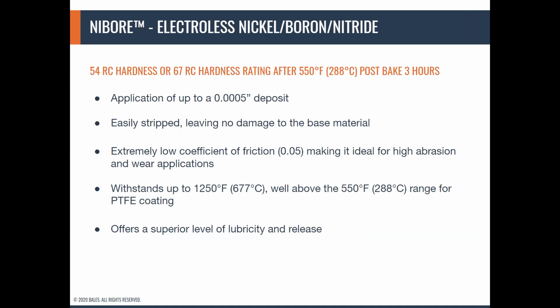Electroless Nickel Boron Nitride, our NIBORE. What's nice about this is now we can add a post-bake option to it. NIBORE, as applied, sits around a 54 Rockwell, which isn't too bad. It's typical of most heat-treated steels. Also, if you post-bake it at 550 for 3 hours, now you've achieved a 67 Rockwell. As you saw in the earlier slide, the hard chrome is a 72 Rockwell. So now you've got excellent lubricity at a hardness near the hard chrome.